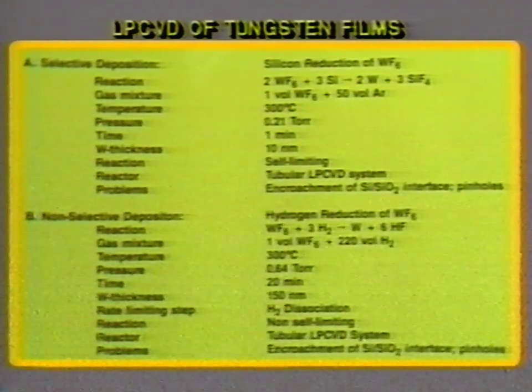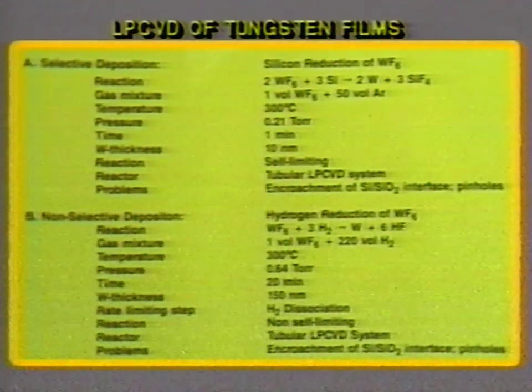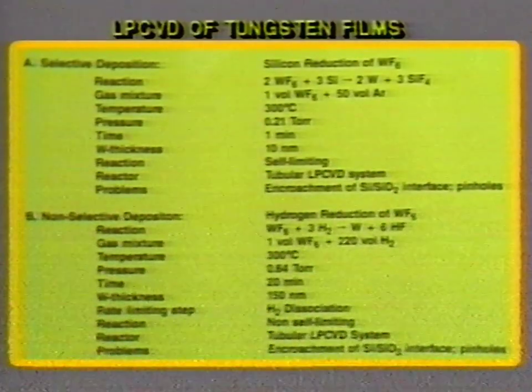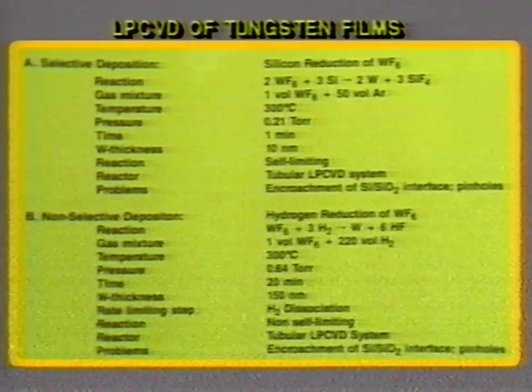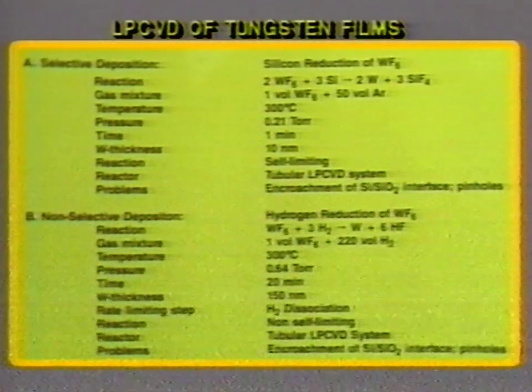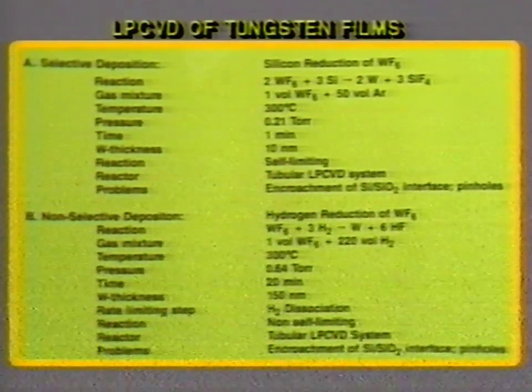One is a selective deposition of tungsten by reduction using the silicon substrate itself. Now the reaction is shown here, and we use the tungsten hexafluoride reacting with silicon to form tungsten metal and SiF4, which is given up in the gas phase. The gas mixture typically is 1 volume of the fluoride to 50 volumes of argon. Temperature is typically 300 degrees C, and it's a very important variable. If you go much beyond that, then you begin to have non-selective depositions. The tungsten tends to deposit not only in the silicon areas, but all over the structure of the oxide-coated substrate.